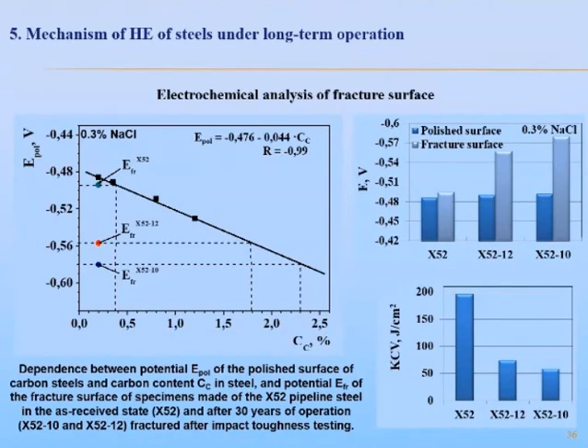And here are also presented results of electrochemical experiments performed on the fracture surface of specimens from X52 pipeline steel in different states, fractured after impact toughness testing with brittle fracture, and on the polished surface. A significant difference between potentials measured on polished and fracture surfaces for post-operated steels was revealed.